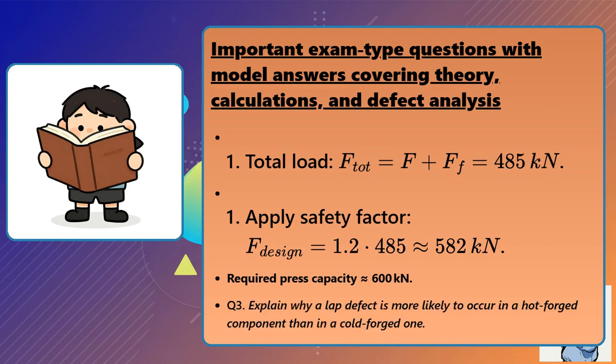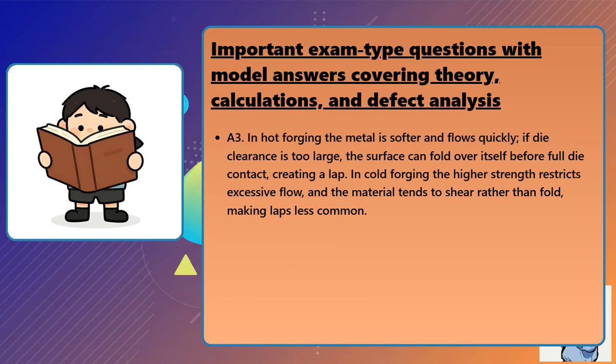Question 3: Explain why a lap defect is more likely to occur in a hot forged component than in a cold forged one. Answer: In hot forging, the metal is softer and flows quickly. If die clearance is too large, the surface can fold over itself before full die contact, creating a lap. In cold forging, the higher strength restricts excessive flow, and the material tends to shear rather than fold, making laps less common.